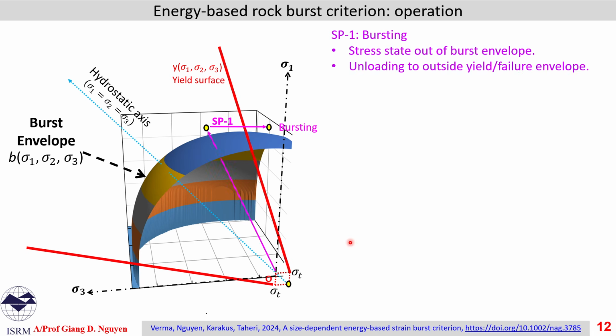We have the first stress path, say that is the stress path going out of the burst envelope. That means the energy stored in the specimen under this stress condition is potentially leading to bursting, because the storage capacity is greater than the dissipation capacity of a single shear band in this case. And if we unload it, meaning we release one principal stress, it is shooting outside the yield surface or failure surface, the red curve here. Then it will indicate bursting because in this case two conditions are met. The initial stress point is outside the burst surface, and the one after stress release is also outside the failure surface, so bursting will happen in this case.